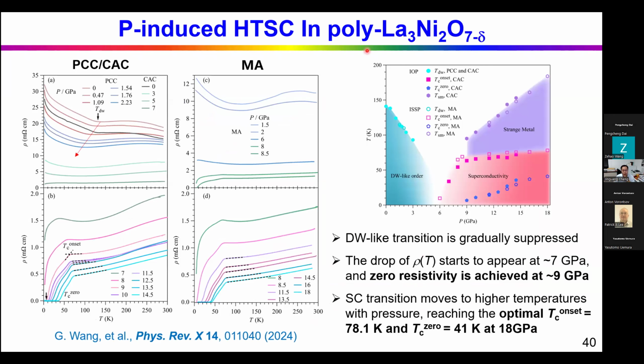First on the polycrystal 327 phase undoped sample. We measured resistivity as a function of temperature under different pressures by using the cubic anvil cell, a piston cylinder cell under lower pressure, and a multi-anvil. We measured 2 samples, this one measured in IOP, and this one measured in ISSP, University of Tokyo. So basically, the result is quite reproducible. We started to observe a resistivity drop around 7 gigapascal, and then this drop becomes stronger, and at 9 gigapascal we can reach zero resistivity.